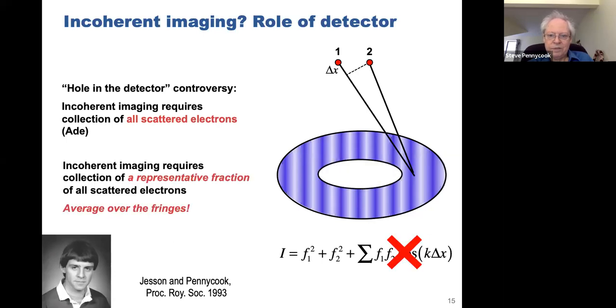But Dave, or we worked out, in fact, that you don't need all of the electrons. You just need to sample enough. You just need to average the diffraction pattern over a large annular detector. So you cut a big hole in it and all these cross terms disappear. And you get an incoherent image, a sum of the intensity scattered from the different atoms. Well, that's not the end of the story. Of course, you've got thickness to think about.